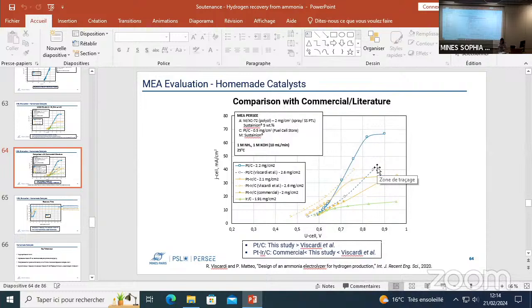Okay, one other point, and then we have to stop for time reasons. There was also the issue that you had when you were using Sustainion, that you had oxidation when you went up to quite high concentrations in your catalyst ink. So this is something that you put to one side. You mentioned that for the Sustainion membrane you did the washing to remove the chloride. Corrected in the thesis. But you don't do that when you use the ionomer. Yes. But you could make your ink and then simply flow electrolyte through to wash out the chloride. This is something that you could think about doing.